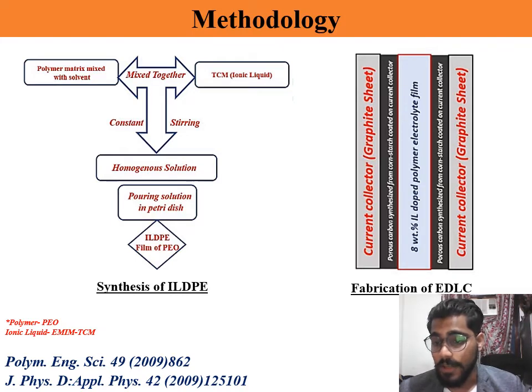The cornstarch biopolymers as a porous carbon was mixed with PVDF-HFP binder for making the conductive paste. The ratio of the carbon to binders was 80 to 20%. The electrodes were finally fabricated by the coating of the conductive paste over these graphite sheets and was kept overnight at certain temperature. And finally, we measured the supercapacitor performance using the electrical impedance spectroscopy.